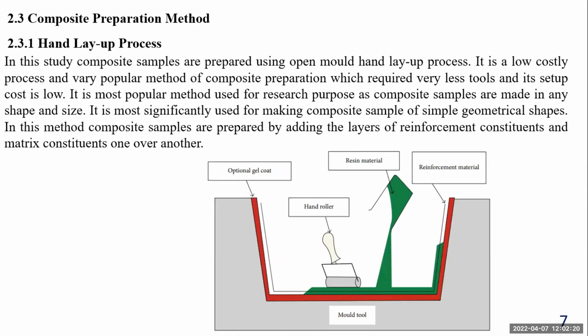For making samples, I am using the hand layup process. It is the cheapest process for making composites. We can make a composite of any size by using this method. The constraint of this method is that the geometrical shape must be simple. I am using the hand layup process with open molding. We add the layers of the fibers and the resin one by one, and the composite samples are prepared by using this method. The curing takes place at room temperature.